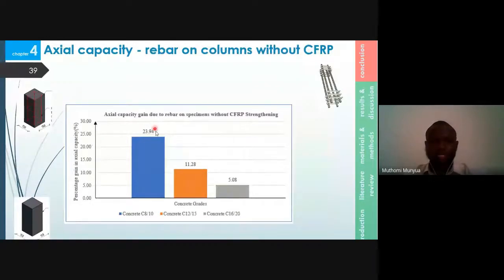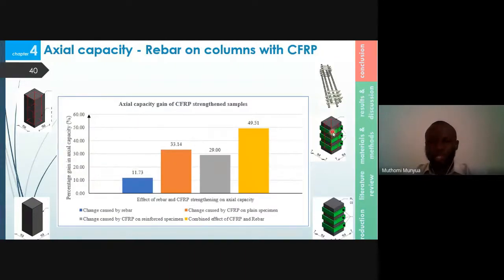In line with the second objective, we compared the effect of CFRP on rebar columns and on columns without CFRP. The trend was similar. Now we wanted to compare the effect of rebar on CFRP strengthening. To do that, this specimen was compared with this to get that. This specimen was compared with this to get the effect of CFRP on plain concrete. This specimen was compared with that to get the effect of CFRP on reinforced concrete, and for the combined effect, this was compared with this.